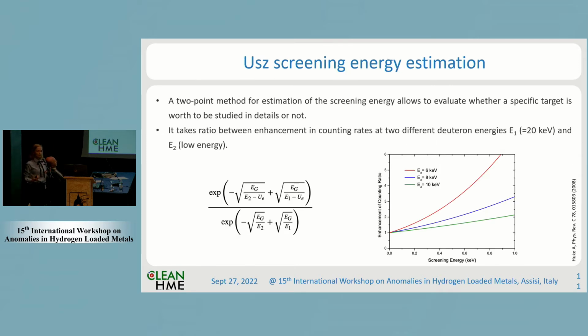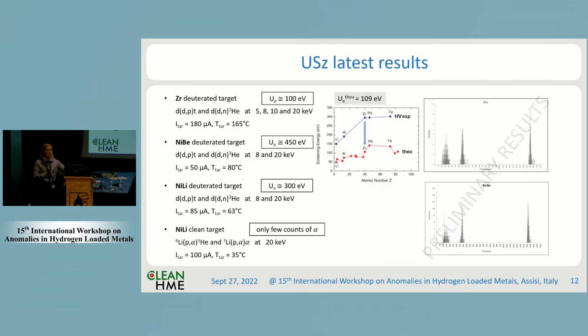And because we want to check the conditions for very different metallic targets and alloys, we would like to have a very fast and quick data analysis. So we introduced this new data analysis in which we have the ratio between enhancement and counting rates at two different deuteron energies. One of them is the energy that we use for the monitor measurement, and the other one is the studied energy.